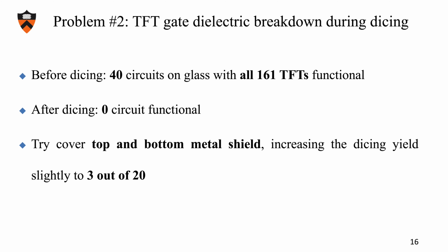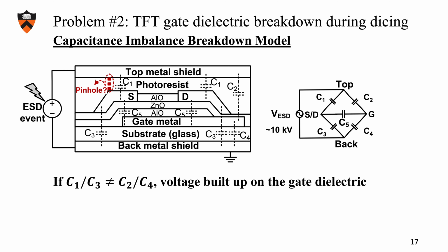We thought about what could cause this problem, and we developed a capacitance imbalance breakdown model. Let's take a look at the model. C1 to C4 are the capacitances between the top or back metal shields and the source, drain, or gate. From the circuit model here, if the ratios C1 over C3 and C2 over C4 are not equal, there will be voltage on the gate dielectric C5. Actually, if all the capacitors are ideal planar capacitors, the ratios would be equal, but in the real world, they are not. So the ratios are not equal and the voltage on the gate dielectric will build up.